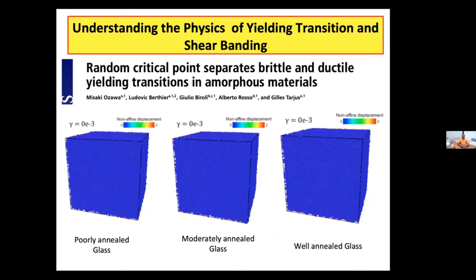Now, understanding this was the dynamical part of structural glasses. This Swap Monte Carlo also gave us the means to understand glasses which are annealed or stabilized to the degree of an experimentally realizable glass, or even sometimes more. So these are extremely well-annealed glasses, and their properties should be comparable to those of experimentally accessible, experimentally tested glasses.